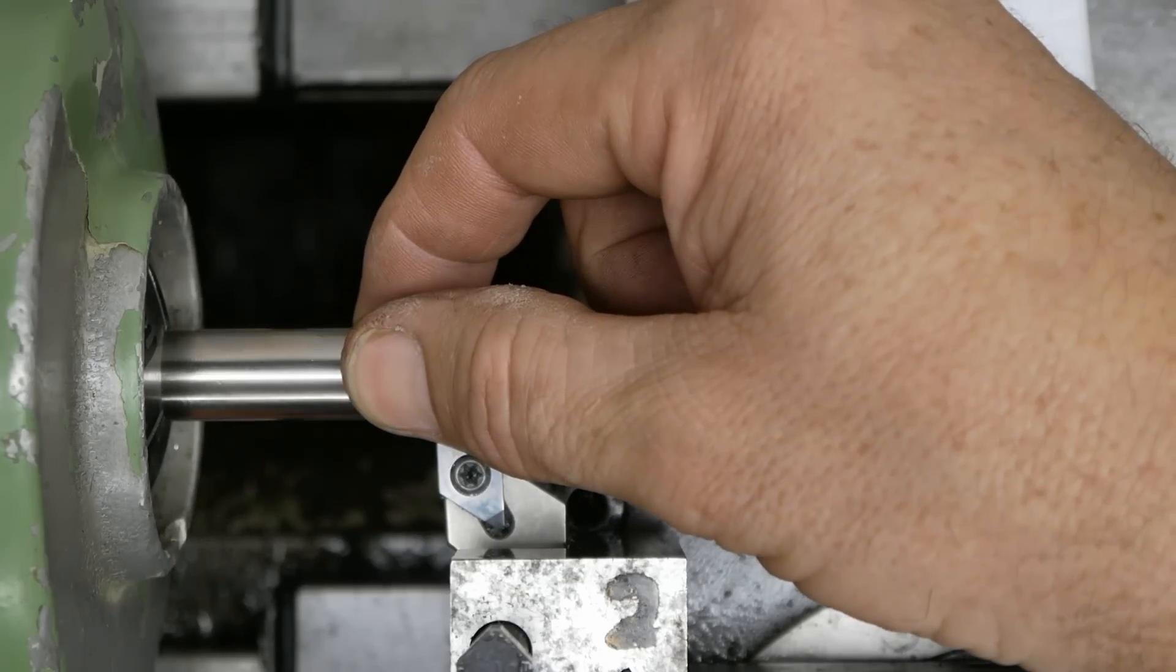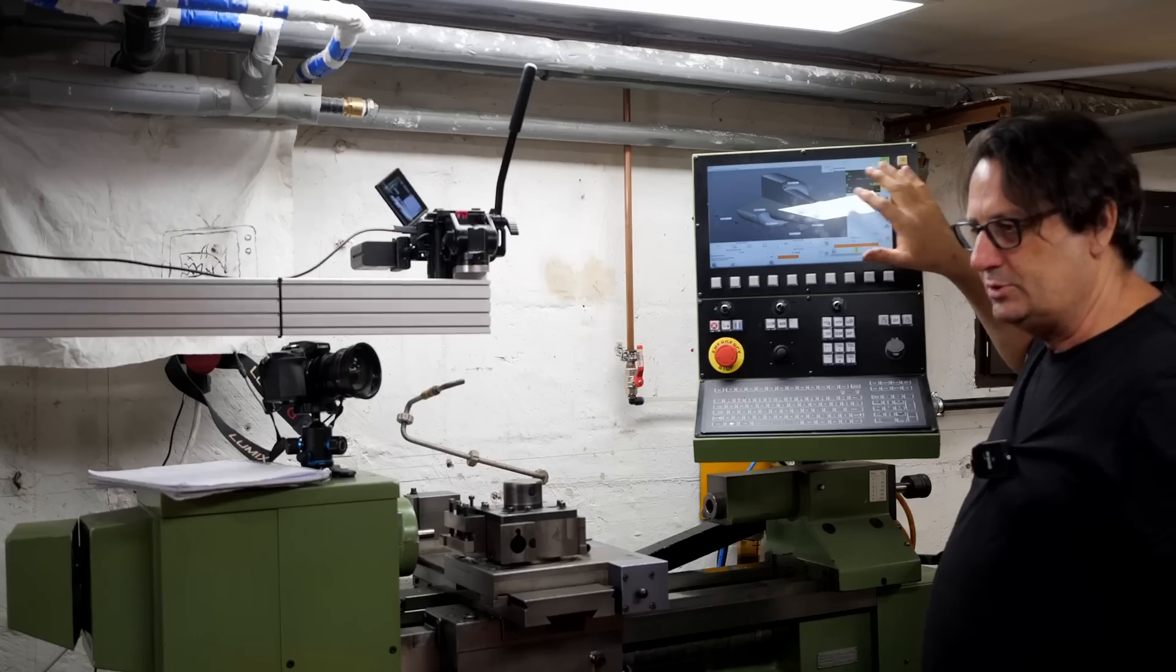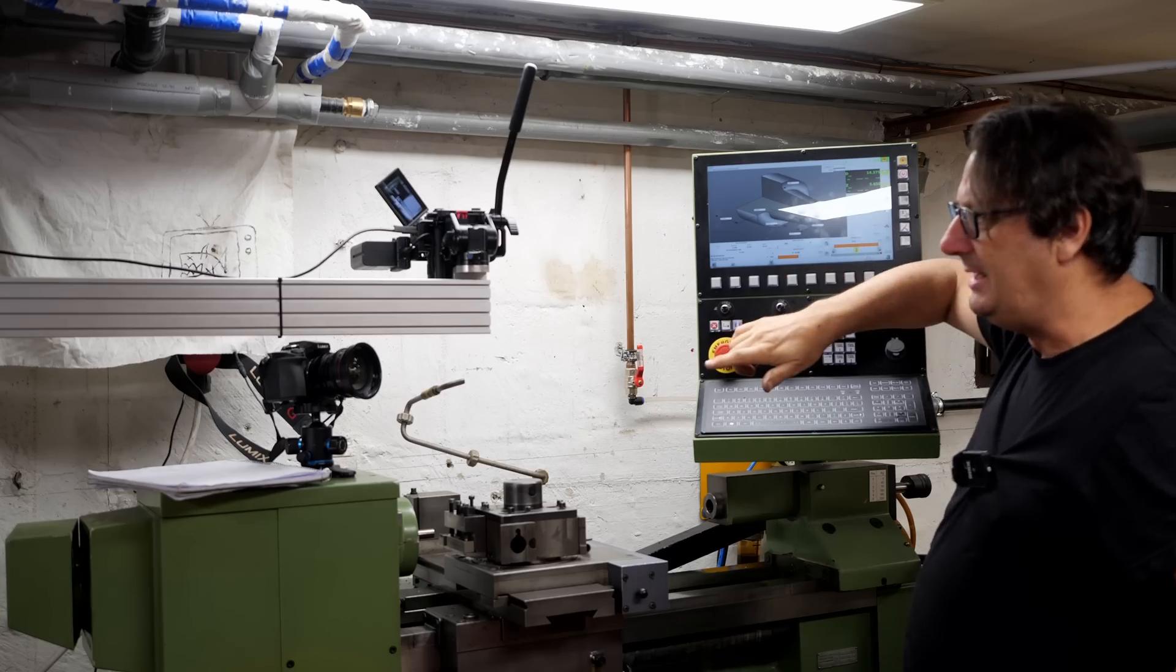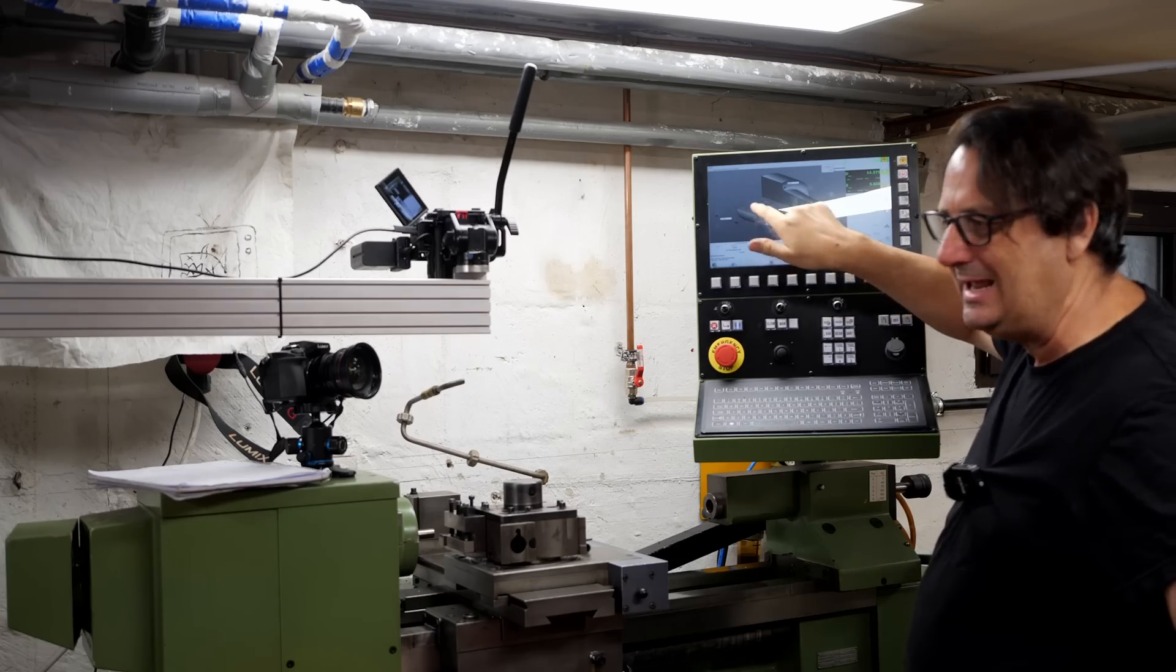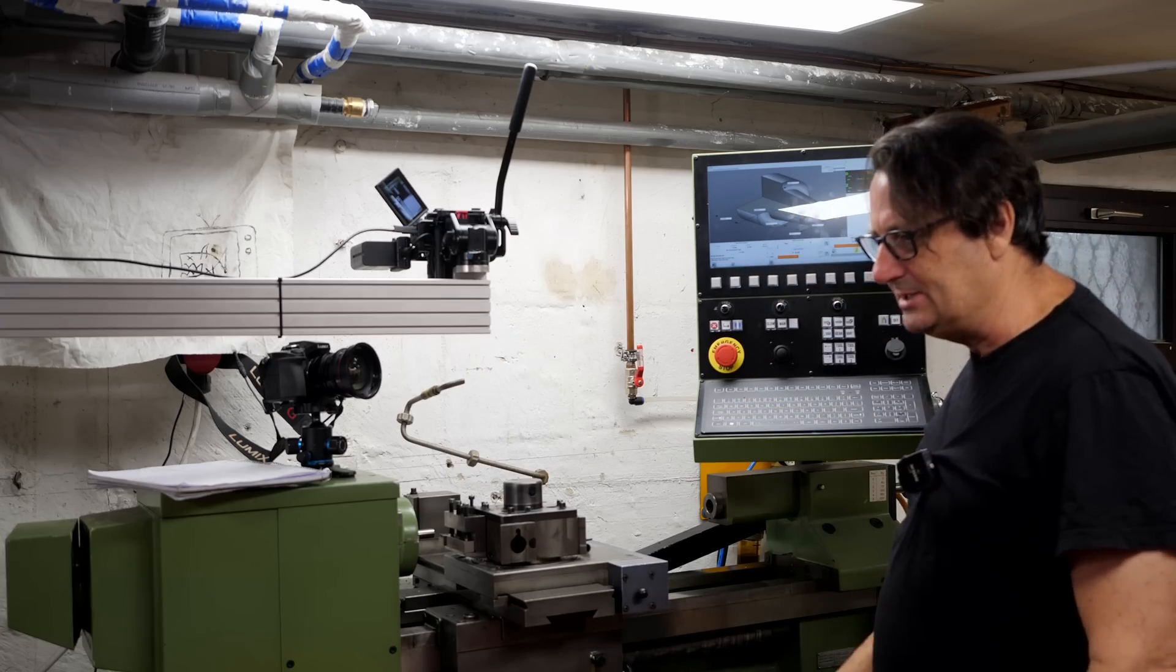The first pass is going to cut air because I don't want anything bad to happen on the first pass while it's still accelerating the spindle. This is one issue with the lathe macros which were programmed by Andy Pugh: there's no delay to let the spindle spool up to speed. Here I'm going to be working around 3000 RPM, which is my max spindle speed. It does take a few seconds for the thing to spool up, so that's why I'm setting it a little bit oversized and having the first pass cutting air, because it'll race off and start cutting straight away and I don't want to be cutting at low surface speed into this material. Here goes nothing. 18 to go.